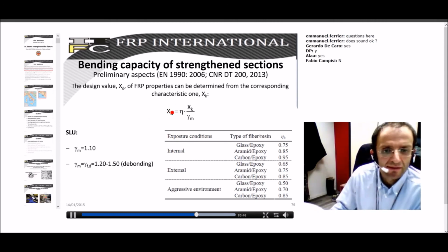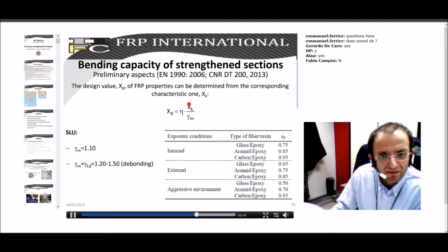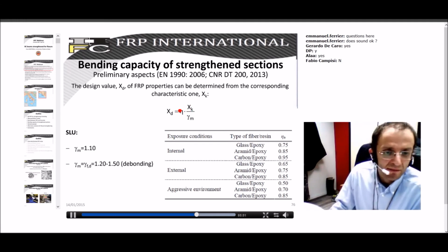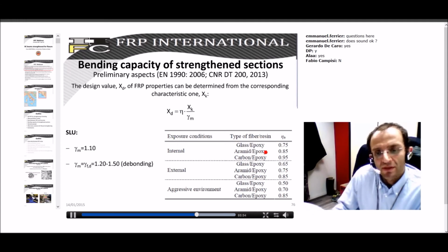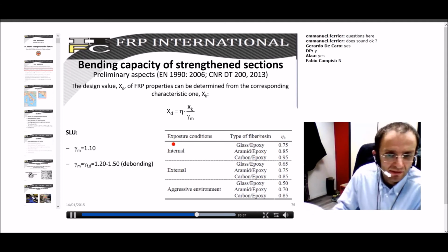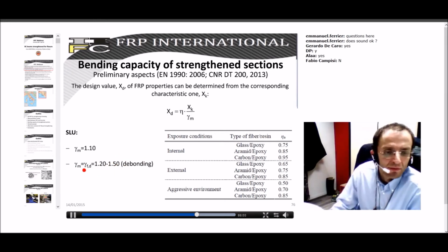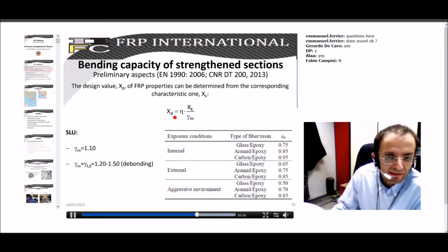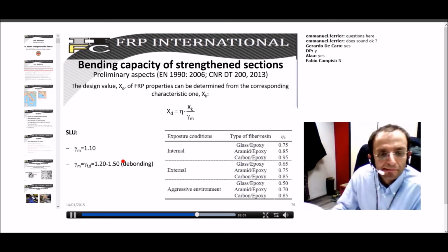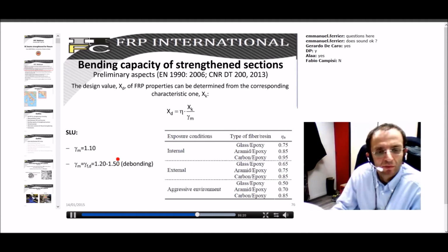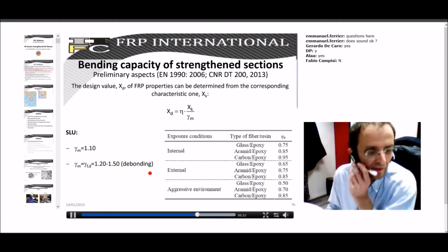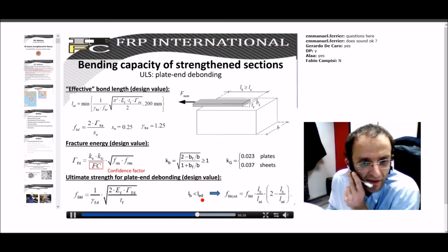For FRP, we can evaluate the design values of properties just starting from the characteristic value, modifying it depending on some factor which depends on the nature of the material, on the working condition, on the kind of phenomenon we are talking about. So if, for instance, you want to evaluate the bonding strength, we have to consider this eta and gamma, the safety factor, which is higher because we have to be safer with respect to the bonding, which is an uncertain phenomenon.